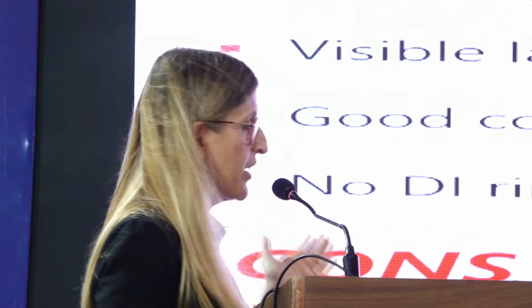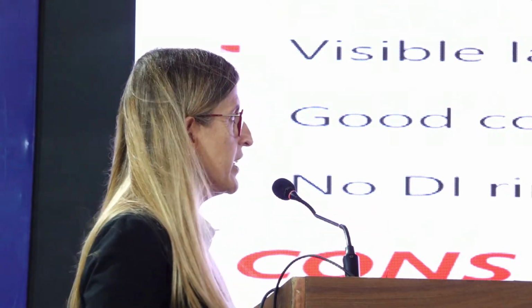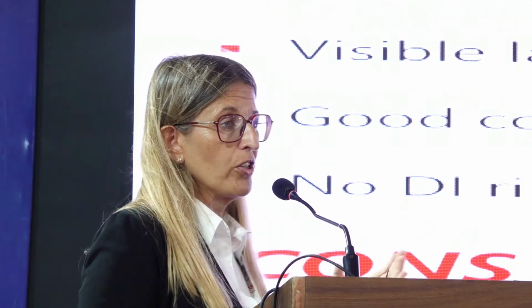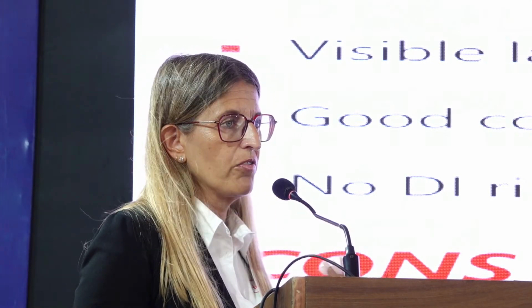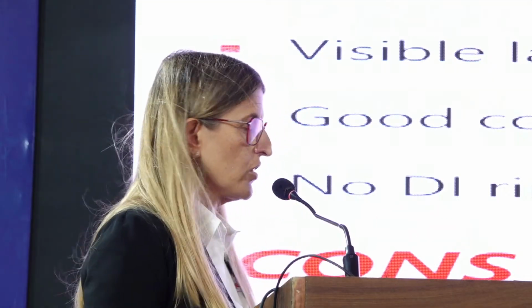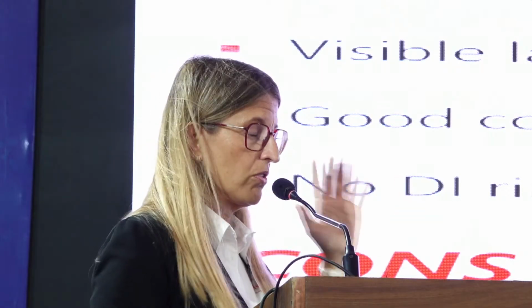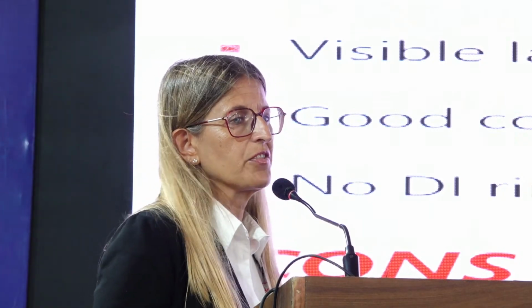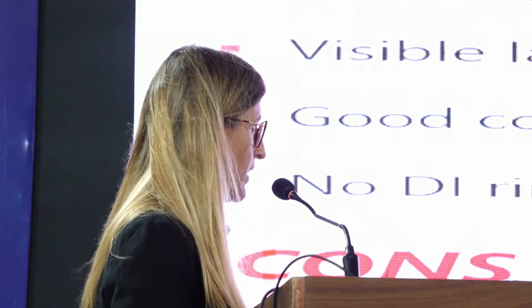You don't need a DI rinse prior to the conversion, and it also has really good protection if you don't paint. These are all the pros, but unfortunately chrome 6 has a really high concern in terms of toxicity for the environment and also for the workers. You also need a wastewater pretreatment, because you need to reduce this chrome 6 to chrome 3. And I don't want to forget that it really requires many rinses and a lot of water, so it is a step with a lot of water consumption. So which are the alternatives of Henkel to these chrome 6 pretreatment lines?